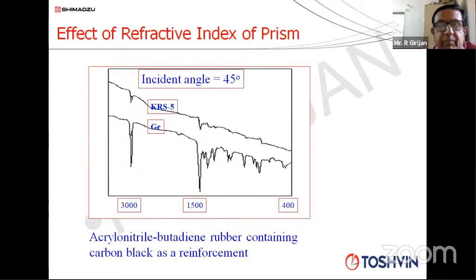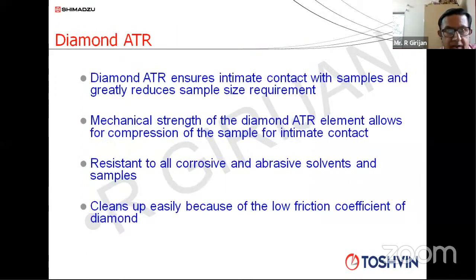So whenever we supply to some rubber industry or any polymer industry where people are analyzing materials containing carbon black, we always advise them to use a germanium prism. Germanium is the only prism which has a higher refractive index compared to carbon black. We also have diamond ATR. Diamond ATR ensures intimate contact with samples and greatly reduces sample size requirement.